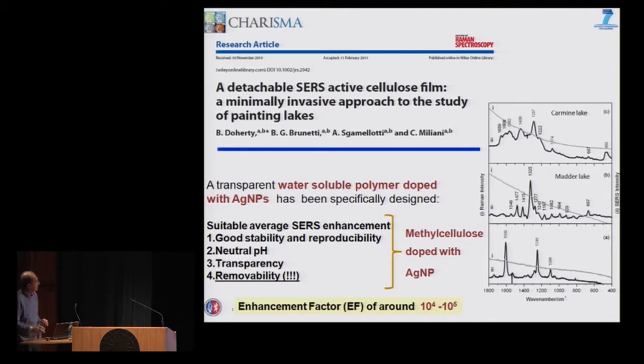The effect is present. The enhancement factor is not very high, as can be achieved in the laboratory in more careful, more appropriate conditions, I would say, but a gain of 10 to the 4, 10 to the 5 is enough to put in evidence the presence of madder lake. This is without the gel, and this is with the gel on the same mock samples. These are all mock samples, no experimentation done in situ.